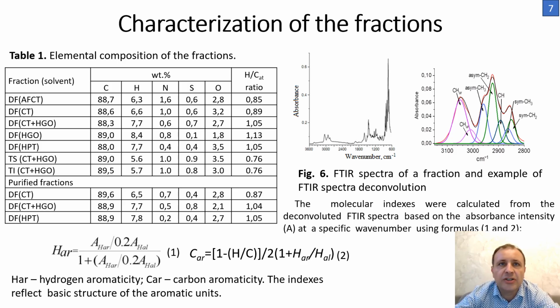Fourier transform infrared spectra indicate the dominance of aromatic compounds through absorption bands in the spectral region of 3000 to 3100 wave numbers. The most characteristic absorption bands between 2800 and 3100 wave numbers were deconvoluted, and semi-quantitative molecular indexes of hydrogen aromaticity and carbon aromaticity were estimated based on the deconvoluted spectra.